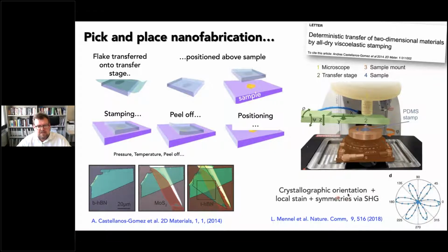So people can use methods like nonlinear optics, where you use short laser pulses to make second harmonic generation. For one of these hexagonal crystals, they're very nonlinear, so they tend to exhibit, if you vary the polarization direction, second harmonic generation only along special directions. So you can figure out the crystalline structure orientation from such a picture. And it turns out if you change the frequency of the laser, you can measure all of these different materials by tuning the laser to different frequencies.